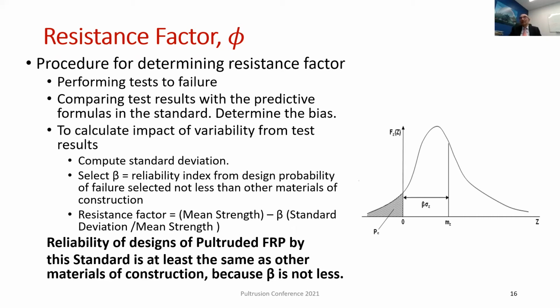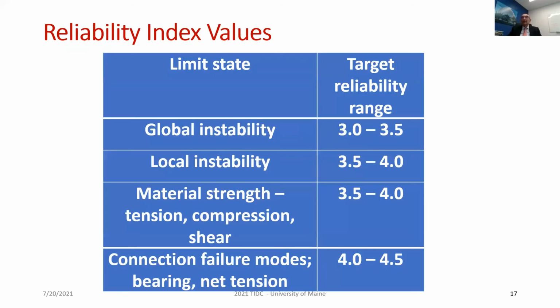And this is the basis why we can claim that structures designed in accordance with this standard, from the standpoint of reliability, are on par with other materials of construction, because we selected the reliability index very similar to those used in other materials of construction. It's variable. For example, general instability is between 3 and 3.5. As you get to local instability, that you don't want to occur at the same time as general instability, you put it further away, 3.5 to 4. Something that you don't want to fail at all is the connection, to which you assign a higher reliability index.